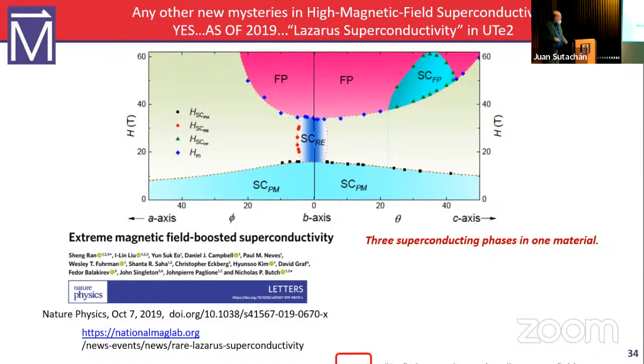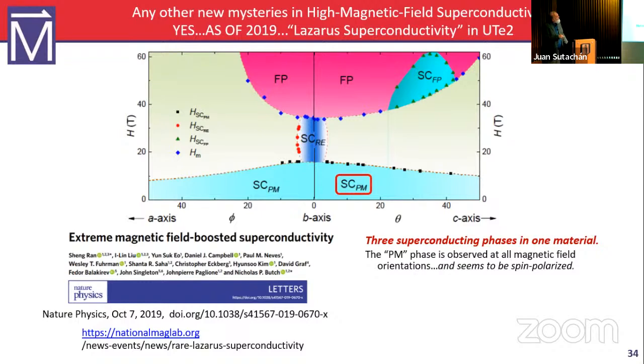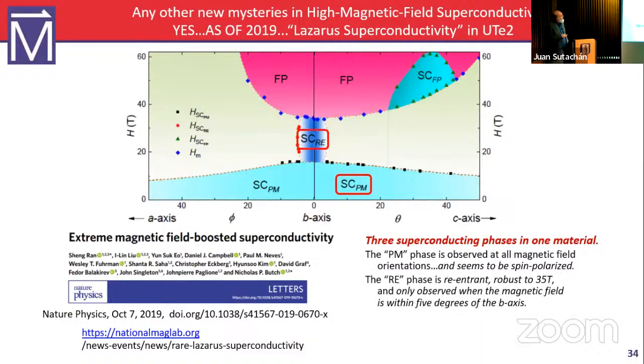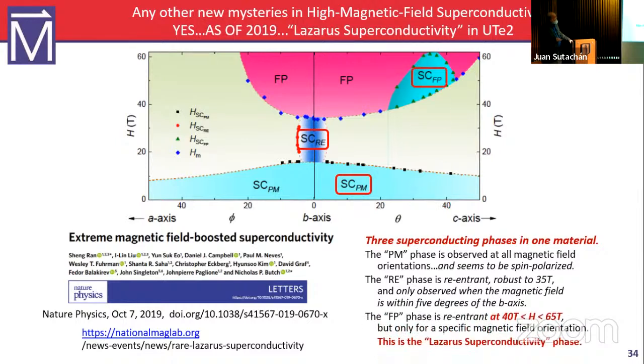Well, this phase is not so crazy. It superconducts at all orientations of magnetic field up to about 17 Tesla. That's what's crazy about it, is you have to go below 1.5 Kelvin to make it superconduct. So even though it's very weak against temperature, it's very strong against the effects of magnetic field. There's a second phase where you have to have the magnetic field within a few degrees of one of the axes. And then the third phase is called Lazarus phase, because the superconductivity lives, and then as you go to higher field, it dies, and then as you go to still higher field, it returns to life.